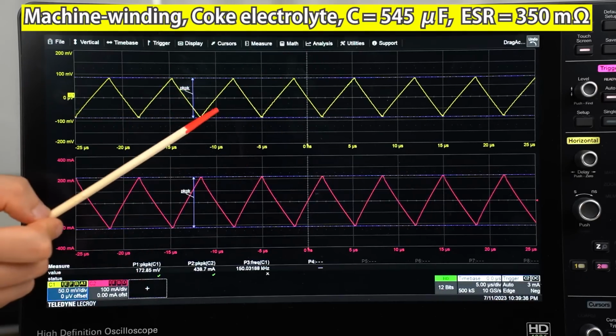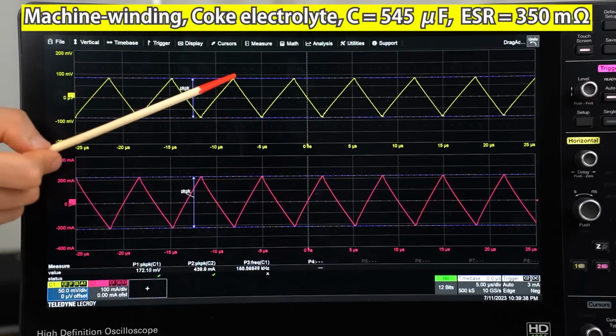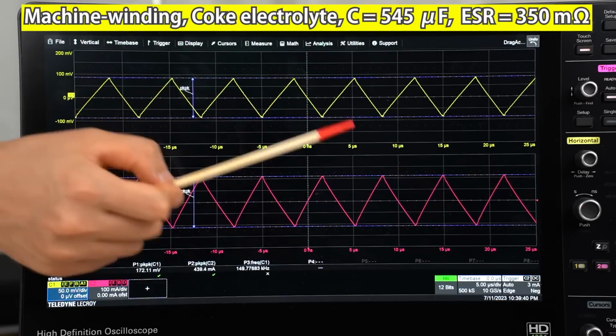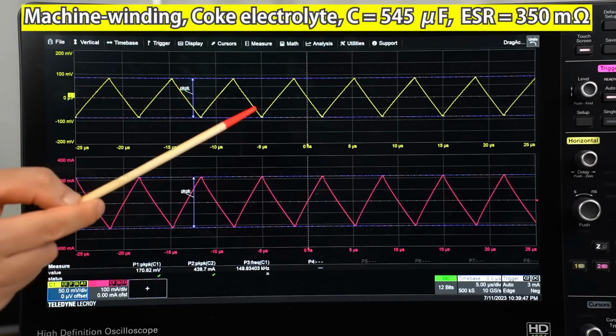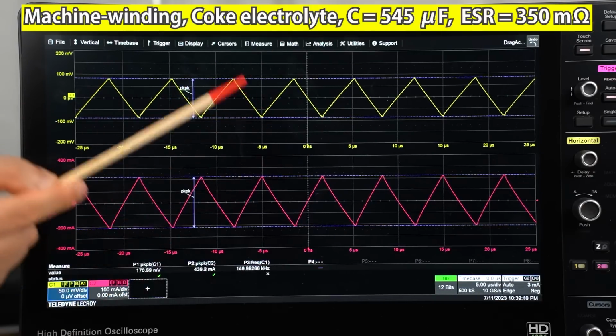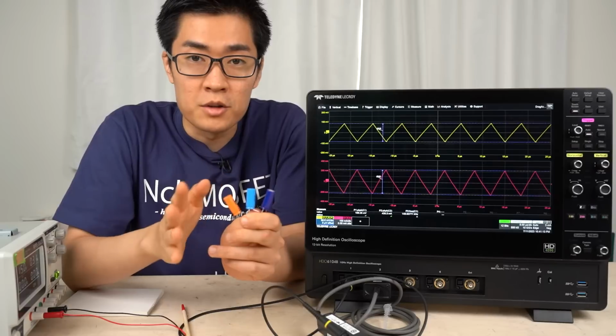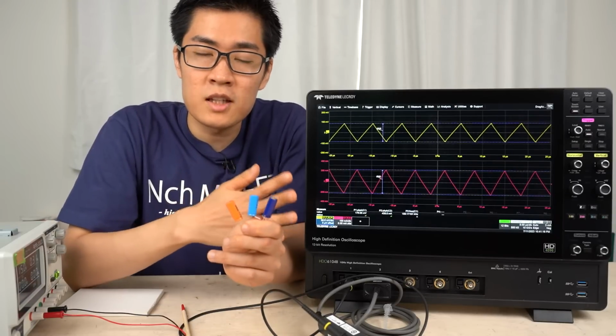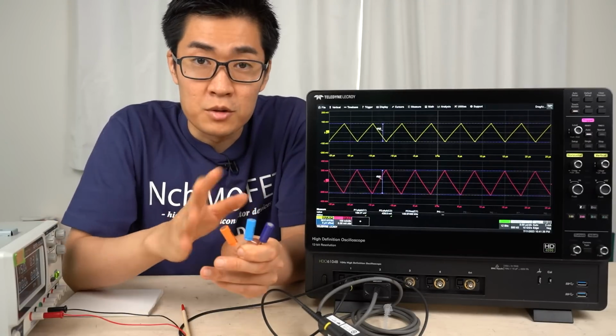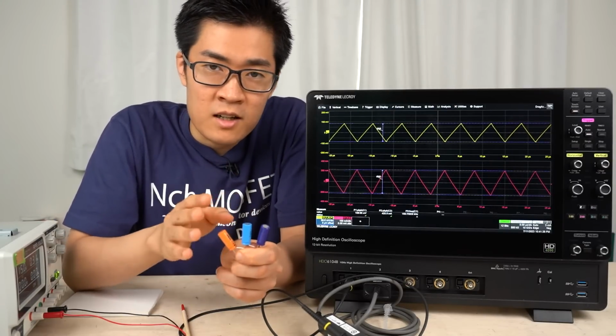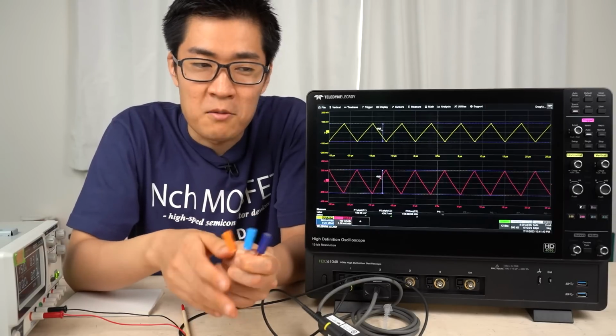The capacitance of these capacitors are almost the same. The difference is caused by the ESR, mostly. This Coke capacitor cannot be put to practical use. It's better to use a capacitor with standard electrolyte. With different electrolyte, the capacitor's characteristics change dramatically. This experiment showed how electrolyte hugely affects the characteristics of a capacitor.